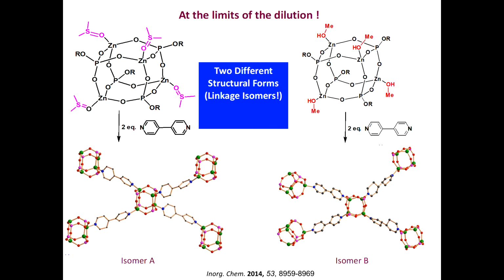So that's when I think Yaghi is publishing a lot of papers using this kind of spacer, like 4,4'-bipyridine. So we borrowed a part of MOF chemistry, but this is not MOF chemistry. MOF chemistry is all about metal complexes. But here you have a main group phosphate, and then you have a linker. So it's kind of a hybridized structure. You have an inorganic phosphate building block, and then you bring in an organic spacer and build this together.